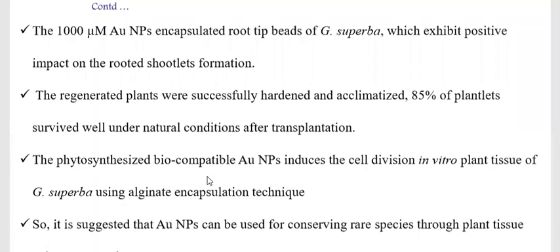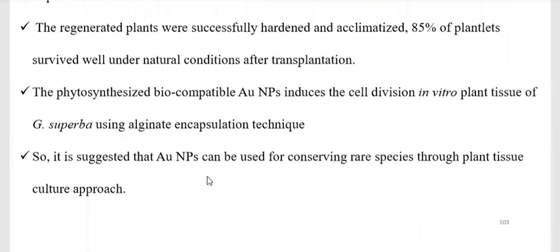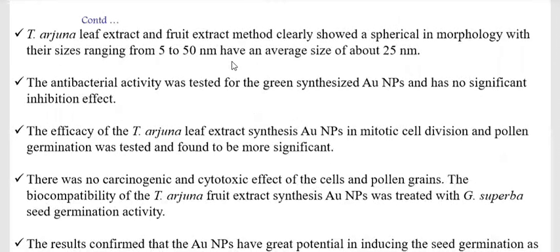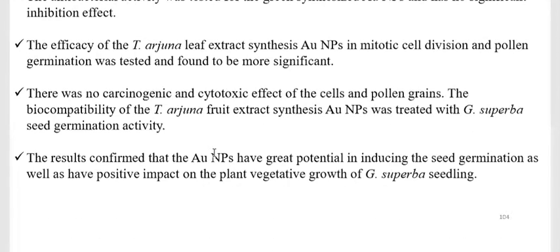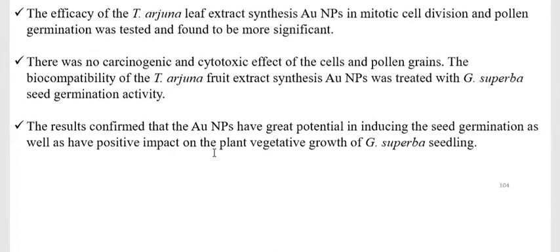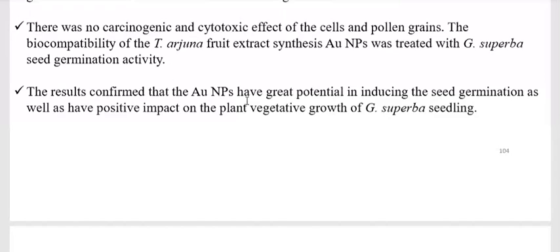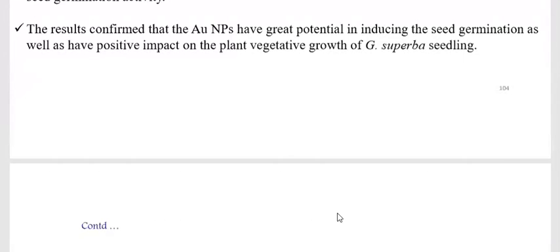The terminalia fruit extract nanoparticles show 5 to 50 nanometers, with an average size of 25 nanometers. They did not show any antibacterial activity. The effect on mitotic cell division and pollen germination was found to be more significant. There is no carcinogenic or cytotoxic effect in the cells of pollen grains as well as mitotic cells. The terminalia fruit extract was used to treat Gloriosa seed germination. The result confirmed great potential to induce seed germination and a positive impact on the vegetative growth of Gloriosa superba seedlings.